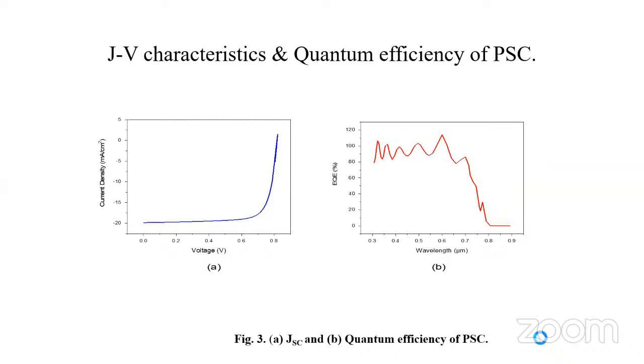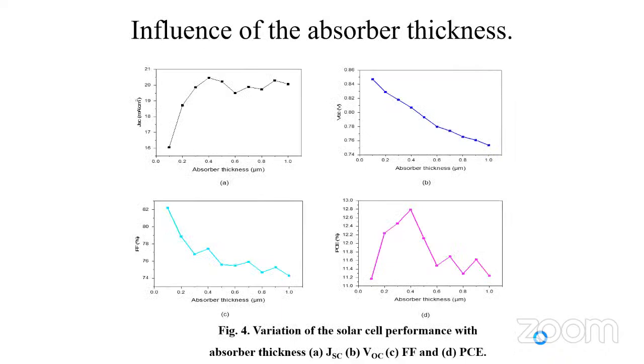As a result of the junction field, a voltage is generated when electrons and holes are accumulated at the anode and the cathode, and a JSC of 19.86, VOC of 0.81, fill factor of 76.81 and a power conversion efficiency of 12.4% is obtained. Absorber thickness: the absorber thickness has a major effect on the device performance. The thickness of the absorber layer is adjusted from 100 to 1000 nanometers to obtain the effect of the absorber layer in the device simulation, while the other parameters are constant, as given in tables 1 and 2.